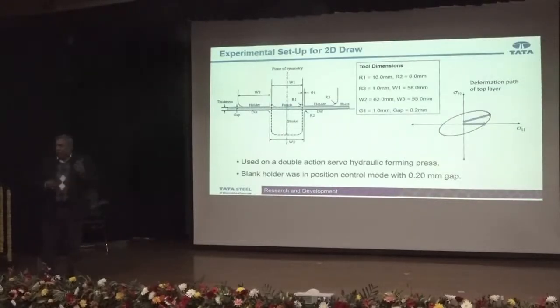So what we did is we designed this experiment. It's a very simple experiment, but a very good one for simulating non-proportional deformation. Here we made a hat section. If you make the hat section, in this region it is going to be bending and unbending, so basically straightening. So the deformation will be plane strain tension, unloading, and then plane strain compression. That is how it is going to be.